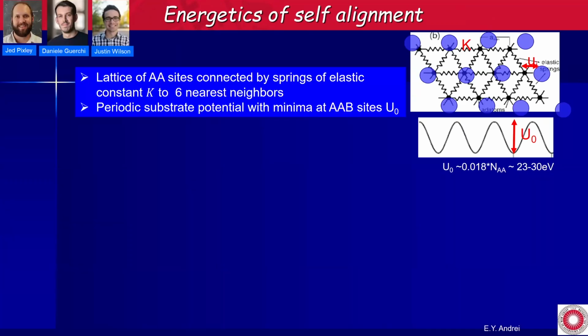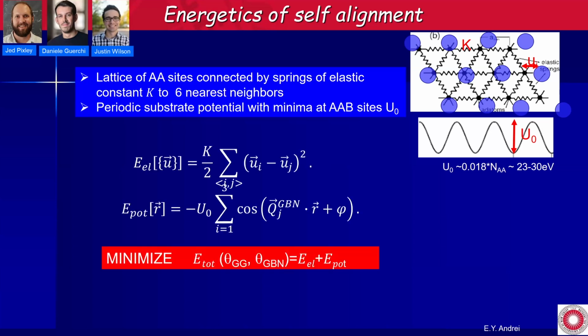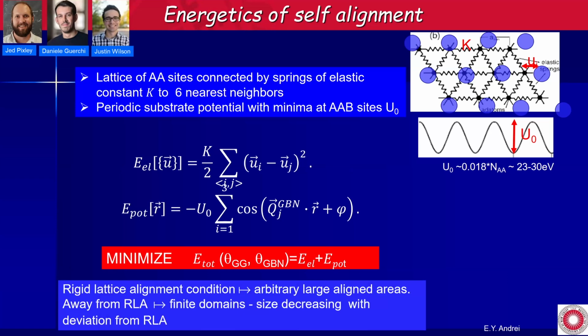Okay, so the energetics of self-alignment are pretty obvious. This was calculated by our theory collaborators, and this is a sample. It's based on a Frenkel-Kontorova model. So you model the AA regions as balls with springs that sit in this van der Waals potential here, in this moiré potential, and then you crank out the energy. You can calculate the elastic energy that it costs for one of these springs to go into a minimum, for all of them, and then you calculate the gain in potential energy. You minimize, and you find that of course, when you are exactly at rigid lattice alignment, you get an infinite size domain, but when you're off it, you get a finite size domain. And you get domains with domain boundaries.